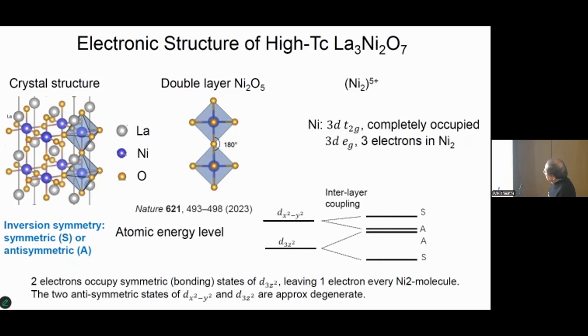And the double layer is splitting, and for the z orbitals I have a symmetric and antisymmetric combination. The splitting is large. For this other orbital, there's a splitting relatively much smaller than this. The reason is that the oxygen between these 2 nickels is pz, with very strong bonding between the top and the bottom nickel, the 3d z square term. So that is the analysis. We can argue that you have 3 electrons, and 2 will occupy this, so we leave 1 such eg electron in this molecule, for these 3 orbitals.